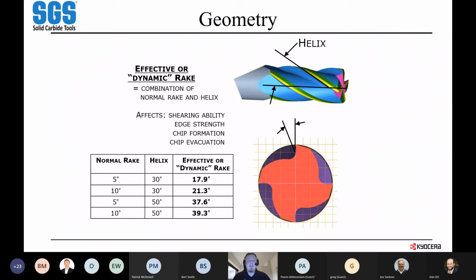So how do you effectively do that? It's based around a combination of the two numbers. So when you look at your normal rake angle and your helix angle, they actually come together to create a dynamic rake. And so you can use this balance between the two in order to get a more effective cutting geometry while boosting rigidity or edge strength.